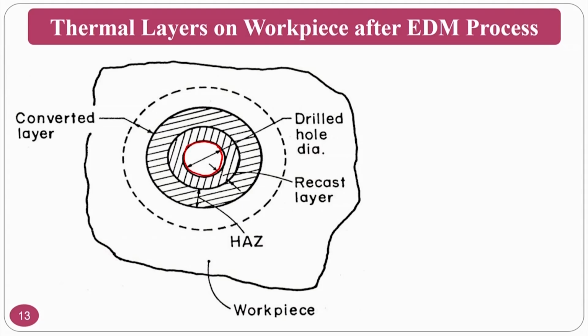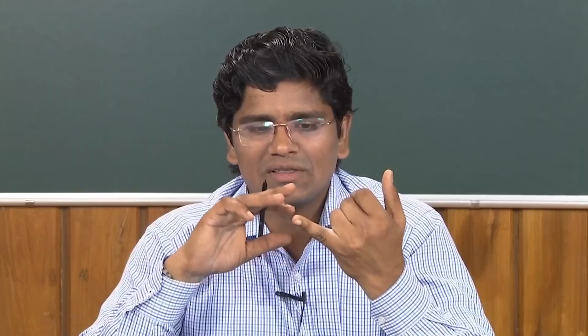Because in the recast layer the temperature is so high, that is developed because of the kinetic energy of the electrons which is converted into thermal energy, the grain structure will be very high. Okay. So, if you see the next layer, that is called heat affected zone, because of the heat that is generated during the hole generation or drilling the hole by EDM process, the molten metal which is unable to go, that is the recast layer, experiences the maximum temperature, because you have seen the workpiece carries heat by the conduction action. Okay. So, by the conduction action heat carries. So, this heat carries, what will happen, there is a grain structure slightly lesser than that one, that is called heat affected zone. You can see here, this is called the heat affected zone, this is recast layer.